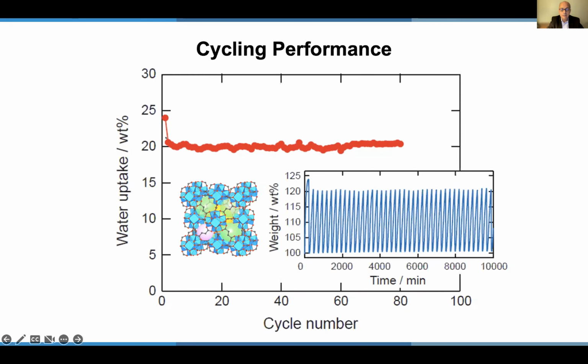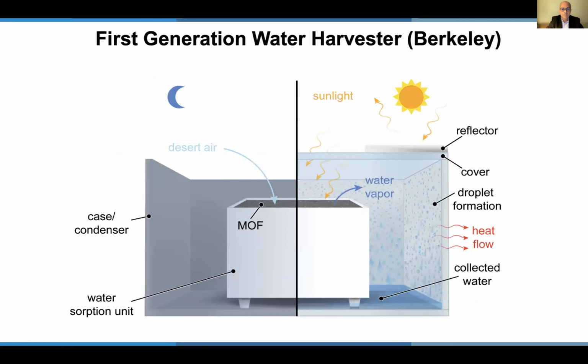This water turns out to be the seed, let's say waters that bind to the hydrophilic sites inside the MOF, and then they act as seeds to bring in other water molecules, and therefore giving rise to the cooperative behavior that I mentioned before. So we wanted to illustrate that this MOF works not just in the lab, but also